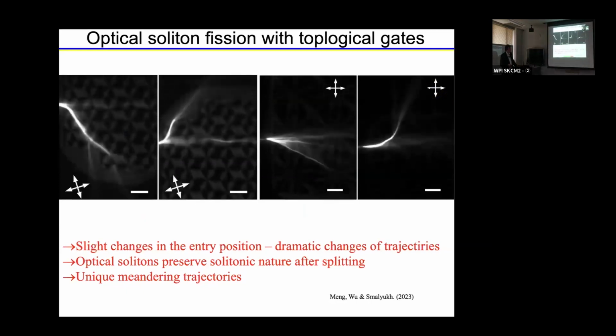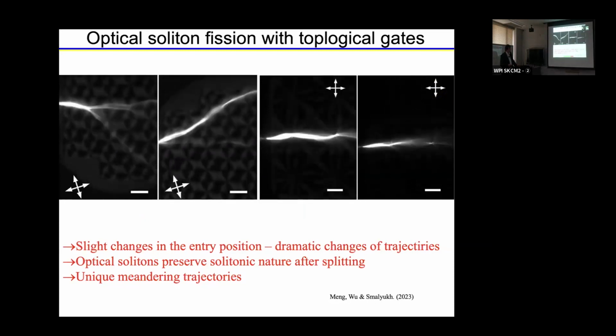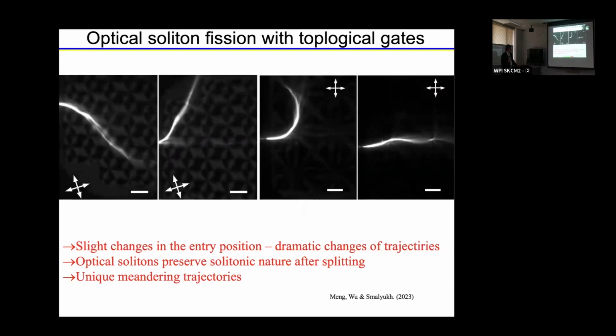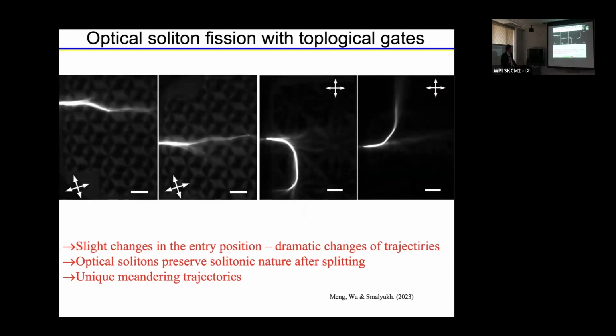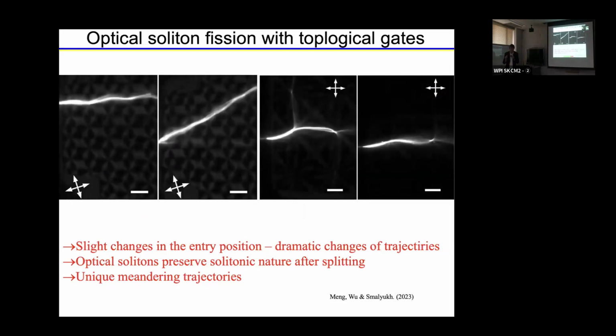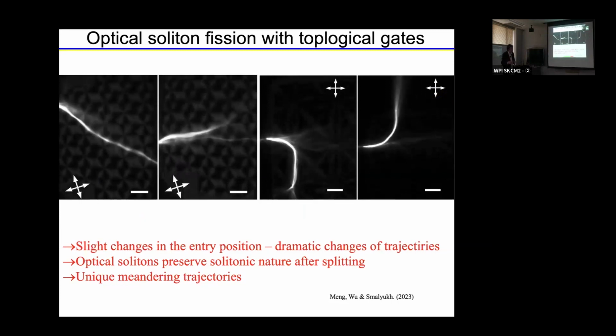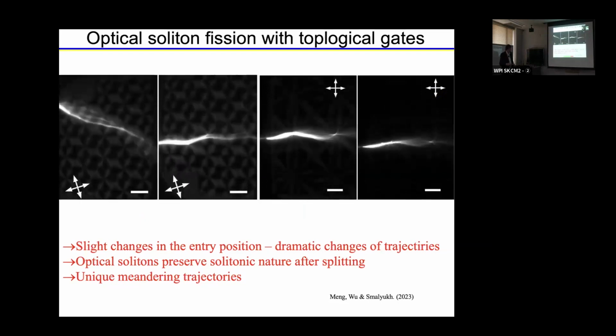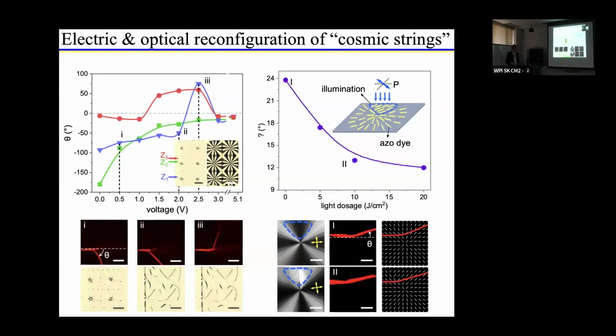And here are some examples of emergent effects. We shine the laser beam in the same direction, but as you adjust by a micron or 2 or 3, and you cross this vortex line from one side to the other, you can see these dramatic responses of the beam propagation pattern that result from this behavior. So we can control the light propagation of these solitonic beams by applying external fields. And here I show how the angle of deflection can be changed by some 180 degrees or even more as we apply voltages on the order of up to 5 volts.